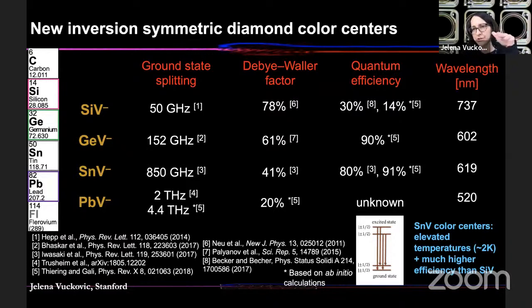They have a configuration that I just showed you previously. So you have 2 missing carbon atoms in diamond, and then you have an impurity sitting between these 2 vacancies. And that impurity is a group 4 atom. And we and others have done work on silicon, germanium, tin, and recently there was some work on lead. And this inversion symmetry is pretty important because to the first order, the system is immune to basically DC Stark shift and static electric fields in the system.